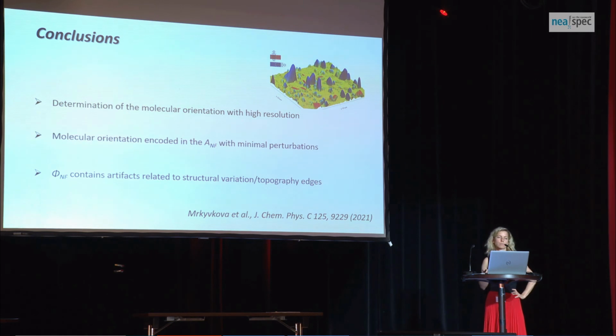Okay, so with this, I would like to conclude my talk. As I was showing, we were able to determine the molecular orientation with a very high resolution, and we found out that the molecular orientation is encoded in the near-field amplitude with minimal perturbation, whereas the near-field phase contains artifacts related to structural variation or topography edges.